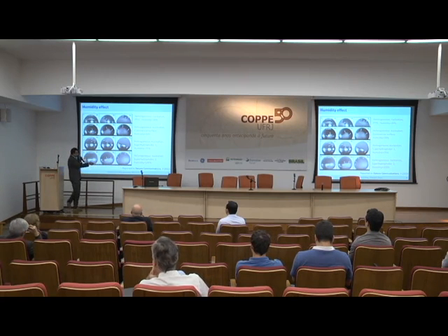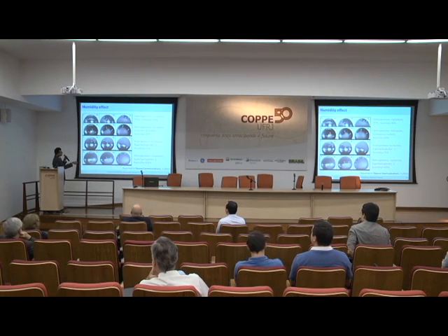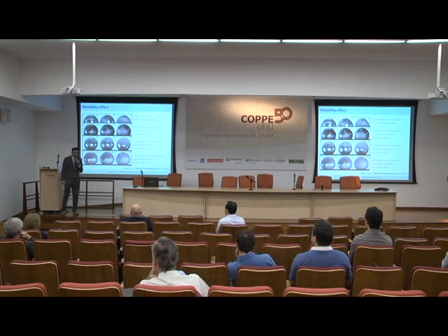Superhydrophobic surface again. Fairly high humidity, 75%. We see homogeneous nucleation. So high contact angle with evaporation is bad. It's giving you homogeneous nucleation. But if I make the environment saturated, 100% humidity, that means kill evaporation, I get back my heterogeneous nucleation. So this gives us the first good conclusion that evaporation during freezing is important. Yes?